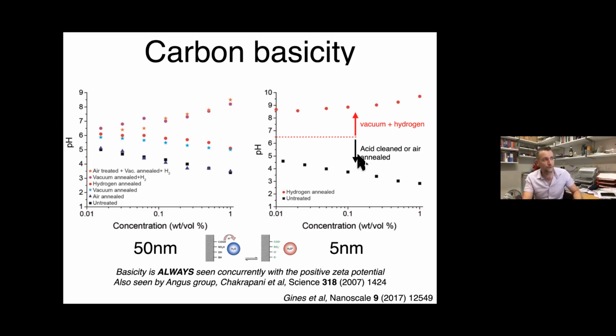And the thing is, if you do it on smaller particles, it's much more extreme. Yeah, you see here, the negative is about the same, but the carbon basicity is way stronger in the 5 nanometers over the 50 nanometers. And again, it's related to the concentration of sp2 on the surface. And so full disclosure, Angus's group years ago saw this and published it in Science, right? And they attributed it to surface conductivity. I don't think so. I think they saw the same thing as us, but I think the reason is not true. So what happened is that they did again a hydrogen plasma, and I think you graphitize when you do that, and you might not see a great big difference in the Raman, right? It's not that sensitive.